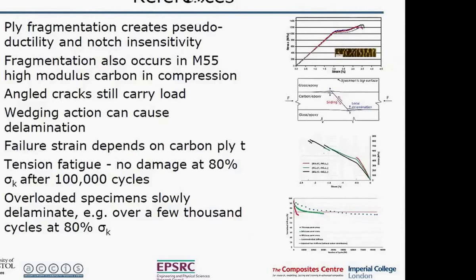And I know you've got constraints around the material systems that you can use because you're using off-the-shelf products. But for example, if you look at this mechanism for compression, which is an interesting one, where you basically have a sliding action, the amount of strain you can generate through that sliding action is going to be contingent on how much delamination will occur between those adjacent plies. That then raises the question, well, what's the sensitivity of the polymer matrix in terms of the level of pseudo-ductility I get under compression? Because presumably a brittle matrix will facilitate delamination and thereby allow sliding potentially to a greater strain than if I have quite a tough material, for example, a thermoplastic or very tough epoxy.